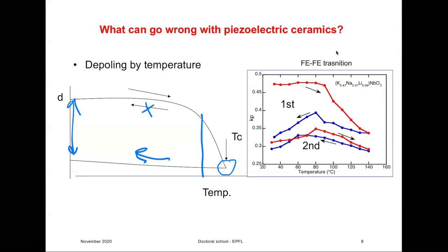What is a good practice very often is that you take your piezoelectric material, you heat it before using it the first time, you heat it to the maximum temperature where you would be using it, anneal it there for a while, then cool it, and then you should usually get a response which should be stable for many, many cycles.